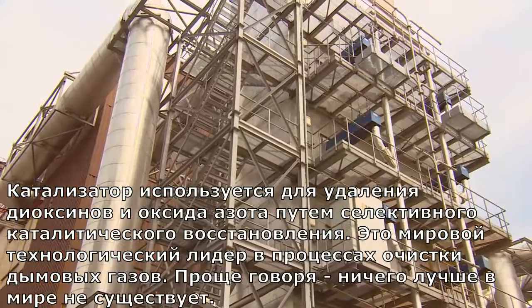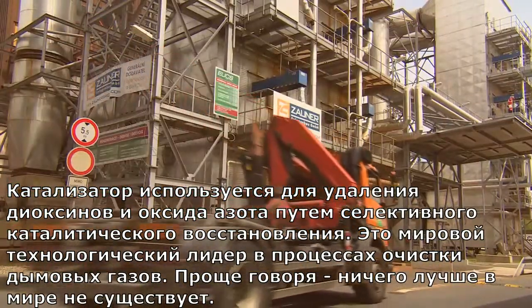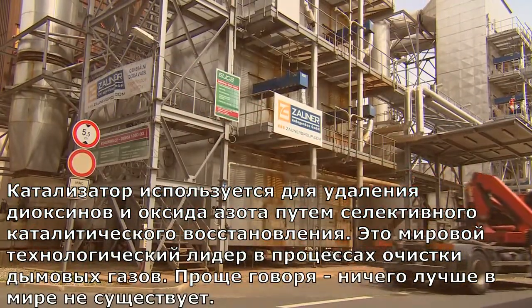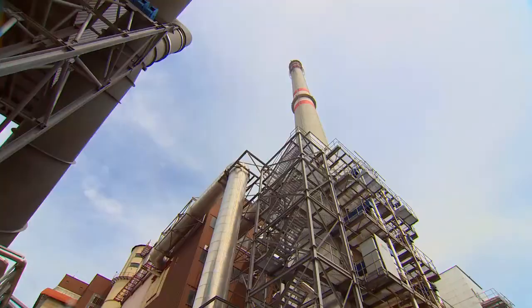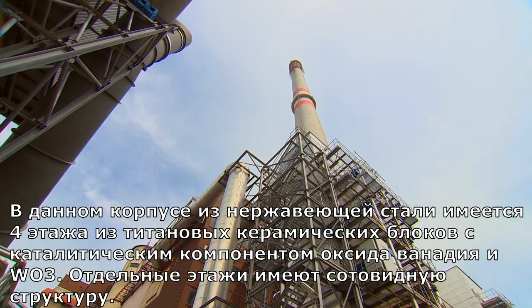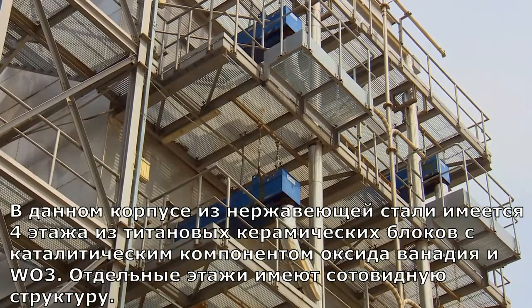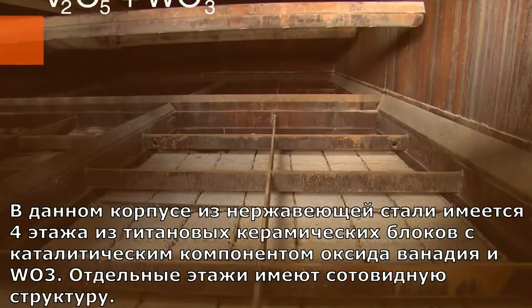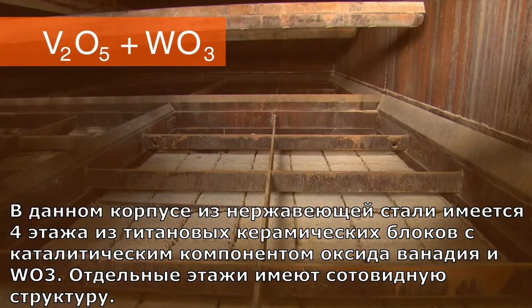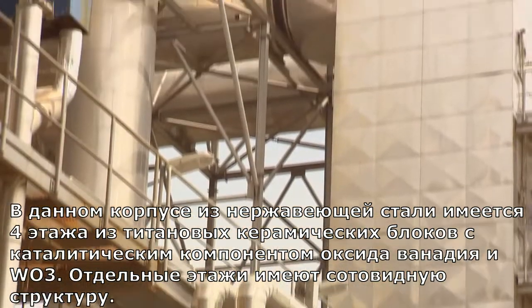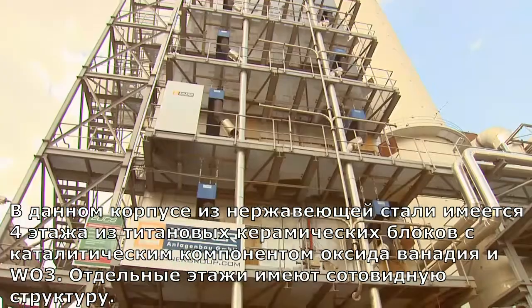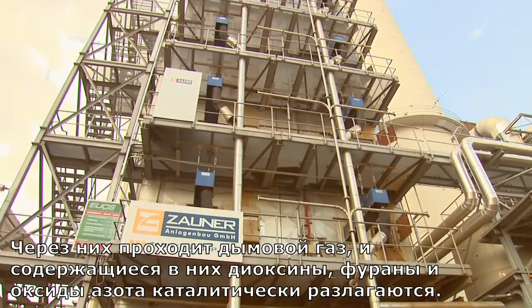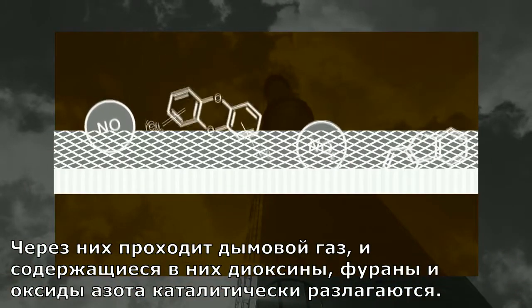It's the worldwide technological leader in flue gas cleaning processes. Simply speaking, nothing better exists. In the stainless steel casing, there are 4 floors of titanium ceramic blocks with the catalytic component of vanadium oxide and tungsten oxide. Individual floors have a honeycomb structure. Flue gas passes through them, and dioxins, furans and nitrogen oxides contained in them are catalytically decomposed.